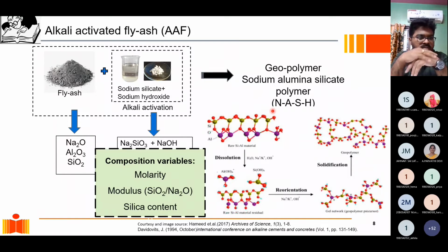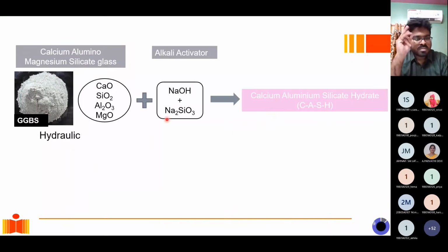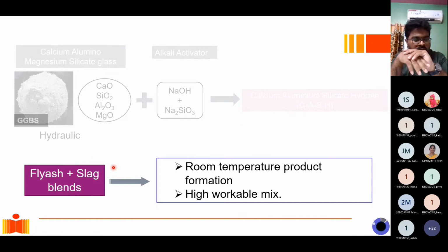Now, the thing is to use them in making concrete. And of course, make that concrete printable. That is the whole exercise. Now, of course, we can also activate slag. Slag is another waste material which comes from refinement of steel or during production of steel. And we use an alkaline activator with slag, which consists of sodium hydroxide and sodium silicate. And what we get is a product called calcium aluminosilicate hydrate. And again, this is a totally cement-free binder, which has good strength and is being used to replace cement.